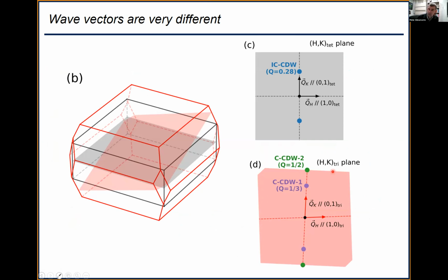Yeah. After that. I mean, it would be worth doing. I think the charge gives you some hint of a better place to look. I mean, of course, a powder looks everywhere simultaneously, but if you want to do a more targeted experiment, if the charge and the spin are coupled, then the wave vector of the spin should be half that of the charge. Yeah. Which means you should look here. Right? Yeah, there should be some phonon softening. I mean, if you form a Bragg peak, then some phonons should soften at the position where you see the Bragg peak. So now we have single crystals. So it might be interesting to do some single crystal inelastic measurement. Yeah, and I would go look here and see if there's a magnetic reflection in a crystal.